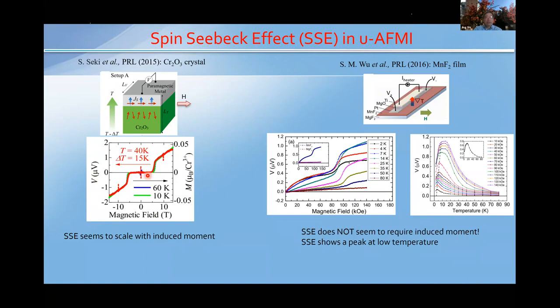So you not only need a magnetic field, but the field also needs to overcome this spin flop transition to induce a finite moment. In some sense, this experiment indicates that the antiferromagnet behaved like a ferromagnet when you look at the spin Seebeck effect: you need an induced moment to have a finite spin Seebeck signal.